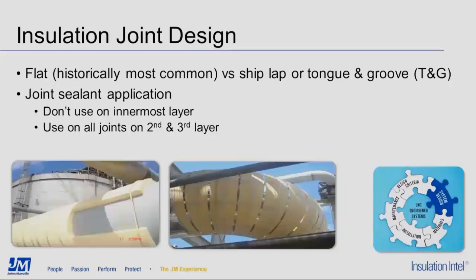The spec should require that joint sealant be applied as a thin, even layer across the entire joint face. The thinness of the joint sealant minimizes the ability of the joint sealant to act as a thermal short and transfer large amounts of heat through it. You want to avoid that. The even application across the entire joint face maximizes both joint strength and joint resistance to water or water vapor movement through the joint. Lastly, joint sealant is typically not used on the innermost layer with PIR insulation, but required on all joints in the second and third layers.